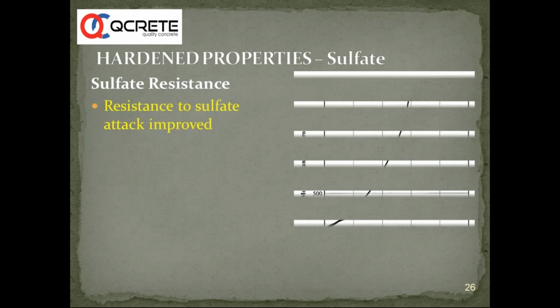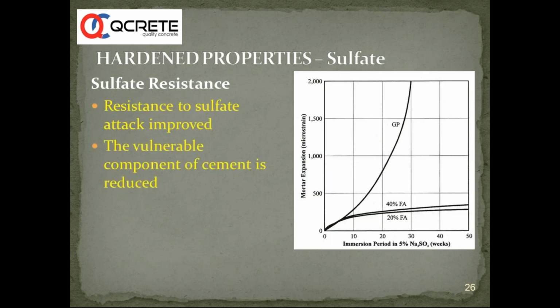As we already discussed, one of the points which we highlighted is that resistance to sulfates is improved. The vulnerable concrete component, CH, is reduced. Like you can see here, a 20% fly ash addition and a 40% fly ash addition have performed significantly well against a general purpose cement or normal cement concrete. So concrete is protected against sulfates when we are using this fly ash. We already discussed that impermeability of concrete is improved.